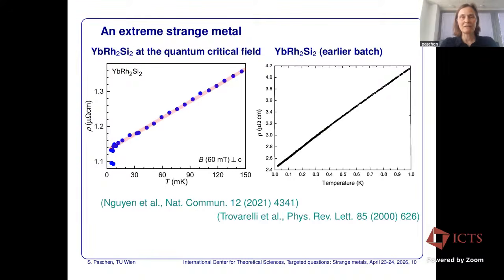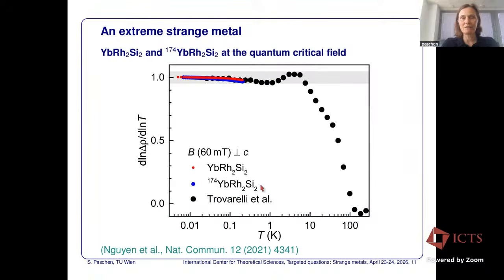So this is the actual resistivity data shown in different scales, because linear resistivity is only shown on one order of magnitude in a linear scale. So I can make several of these plots. That means overall, this linearity actually spans over orders of magnitude. So this is more than 3 orders of magnitude linear exponent within an error bar of 5%.